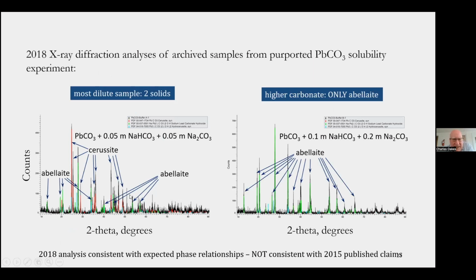X-ray diffraction scan from the government report. Again, he didn't report these things in his actual published paper. He just makes the claim in words with no substantiation. So this is the most dilute point, the one I just said I could be wrong about. Well, the X-ray diffraction scan says I'm right. There are 2 solids in that sample.